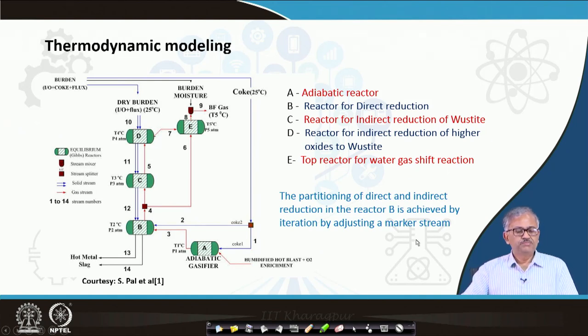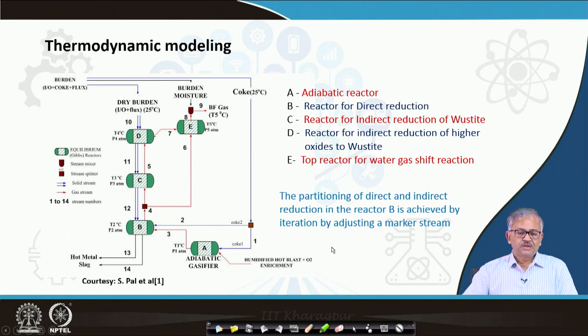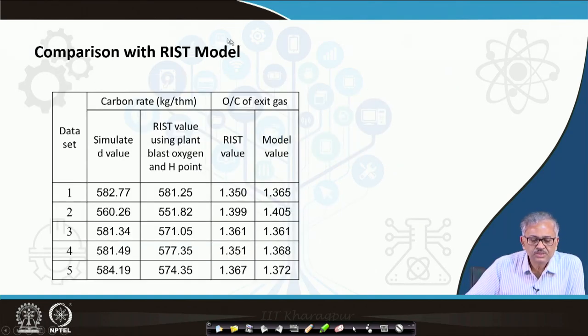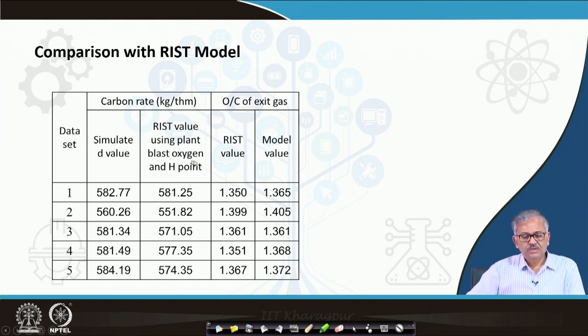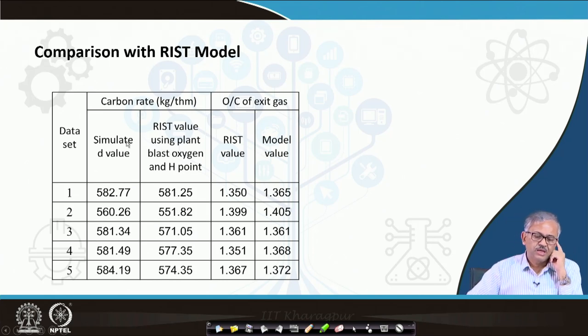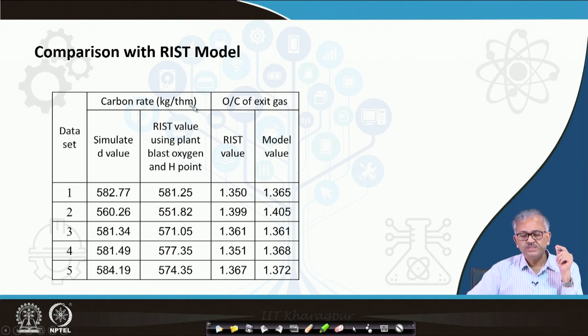This is a simple thermodynamic model, based on the work of Soma Bhopal in his M.Tech thesis at IIT Kharagpur. Comparison with the RIST model shows the simulated value of coke rate matches the RIST diagram value. From the RIST diagram, if you know the oxygen blast and the thermal pinch point, you can calculate the coke rate. For different data sets there is a quite good match between the simulated and RIST values. The O/C in the exit gas also shows a very close match, so this model is working.